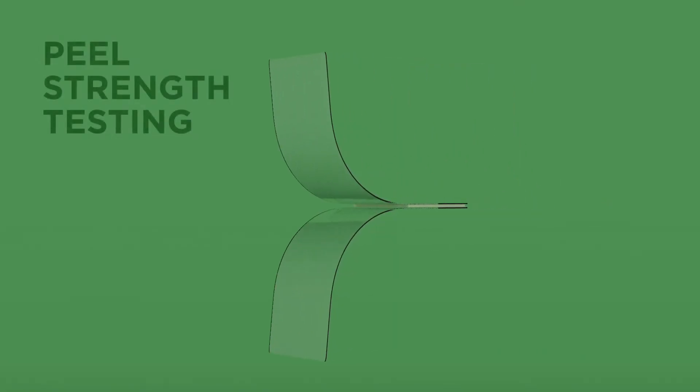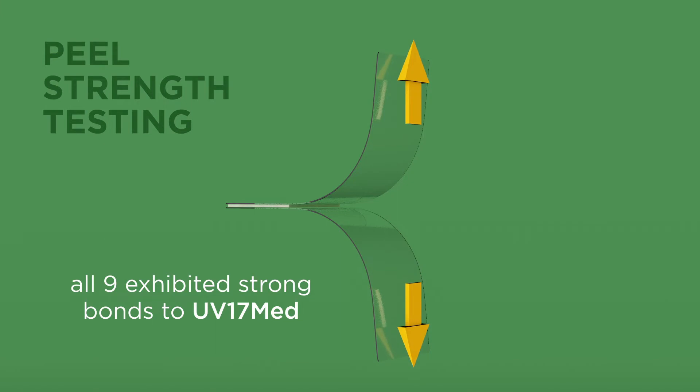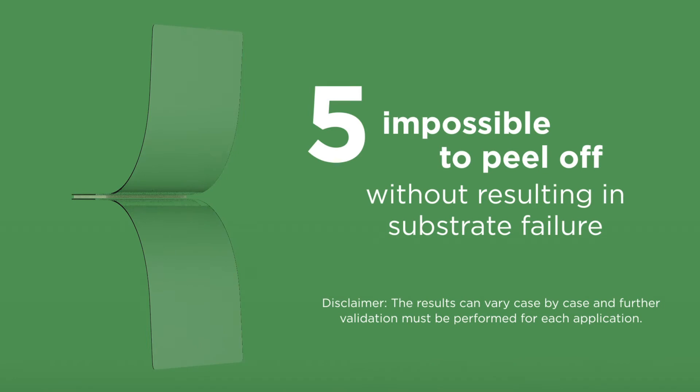UV-17 Med's peel strength was tested on nine different types of TPU films sourced from two suppliers. All nine types of TPU exhibited strong bonds to UV-17 Med. Five of them were impossible to peel off without resulting in substrate failure.